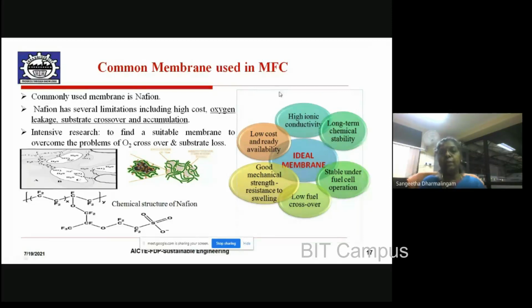Therefore, the ideal membrane is expected to have good ionic conductivity, good chemical stability for long-term use, and good stability in the electrochemical operating condition of the fuel cell. Very low fuel crossover is required of the membrane. Good mechanical properties, resistance to swelling. Too much swelling should not happen, because they are all basically hydrophilic in nature. They absorb a lot of water and their stability goes down. That should not happen. They should not absorb too much water,